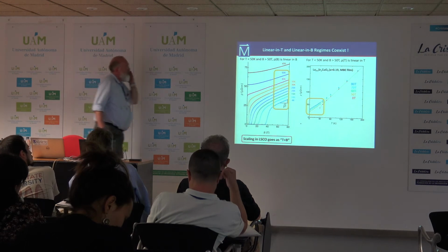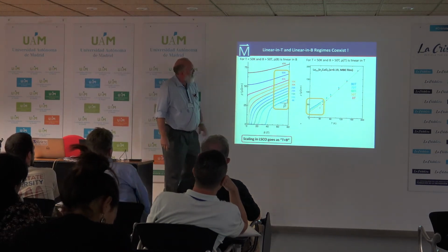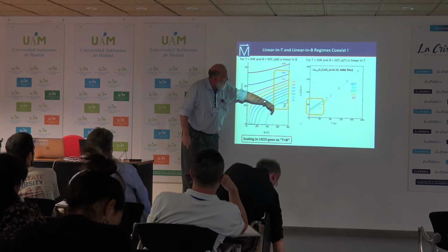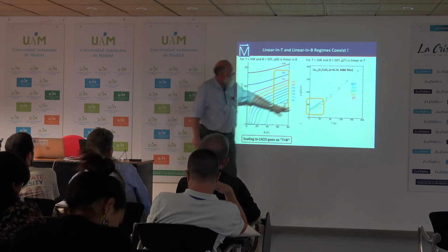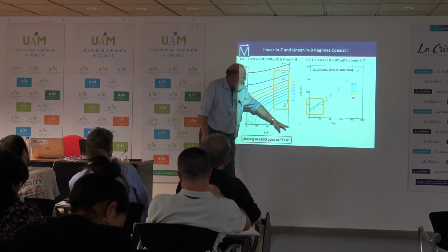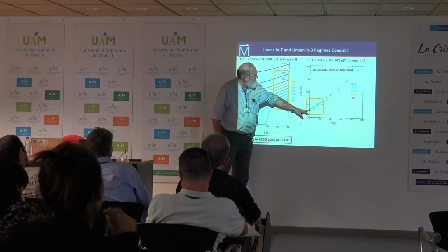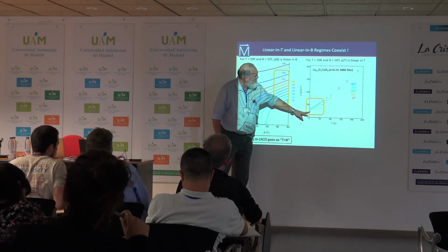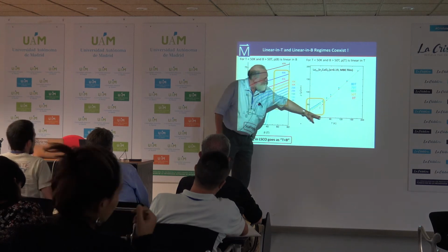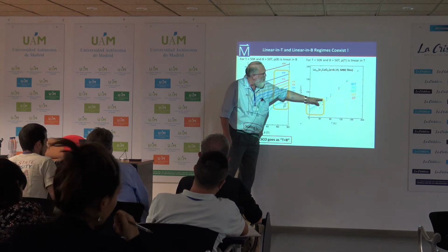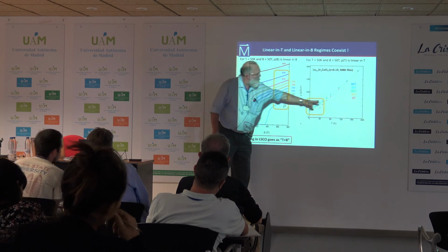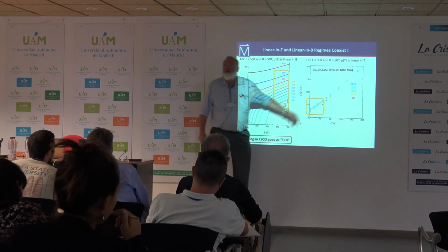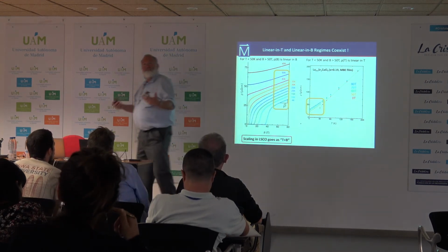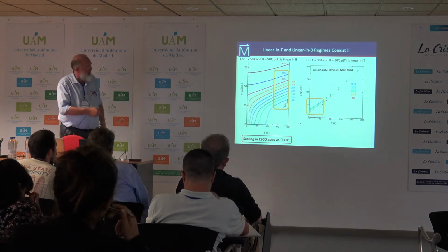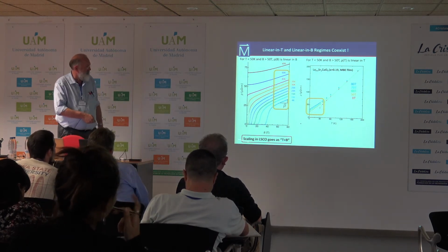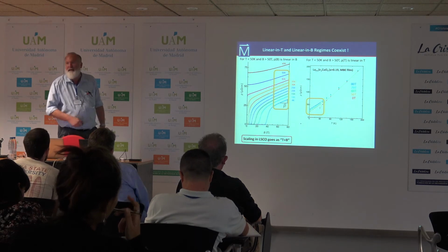And here's the key result. In LSCO, we see linear in H above 50 Tesla. And if we plot the values at 80 Tesla here in blue, 70 Tesla in light blue, 60, 50, you'll notice that over this regime below 50 Kelvin, we've got not only linear in H, but we've got linear in T. So we've got linearity in both of these values, and so it's as if our scaling goes as something like T plus B.